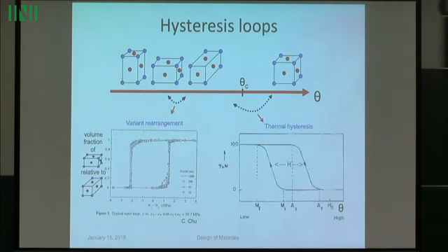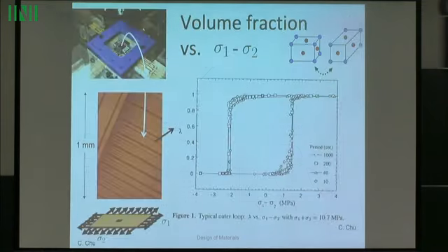Of course, the main thing of interest here will be the transformation from the austenite phase to the martensite phase. All three variants then would be in the low temperature phase. And then you would also get a hysteresis loop. This is the percent of martensite versus temperature. You begin to transform here, you finish here, and so forth back. Usually people in material science fit this by a parallelogram, and they take the half width of the parallelogram to measure the hysteresis.